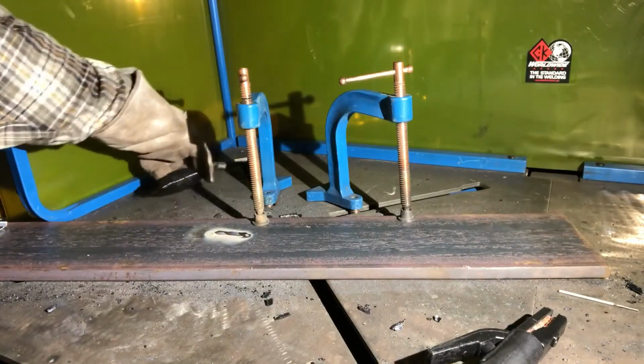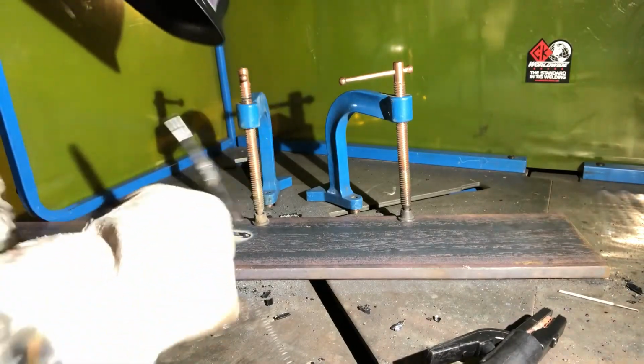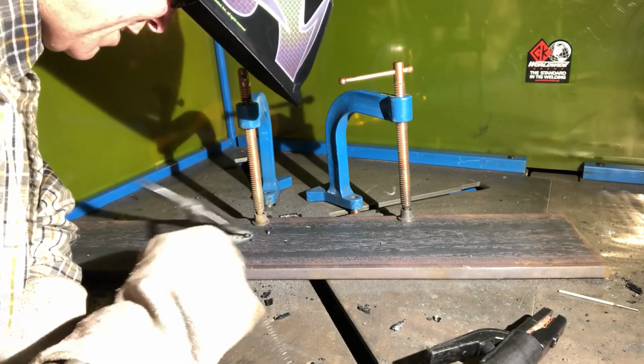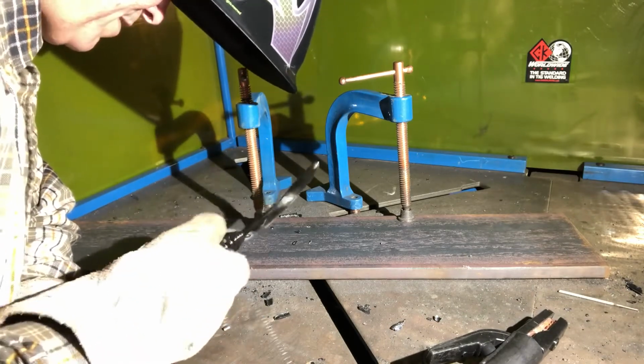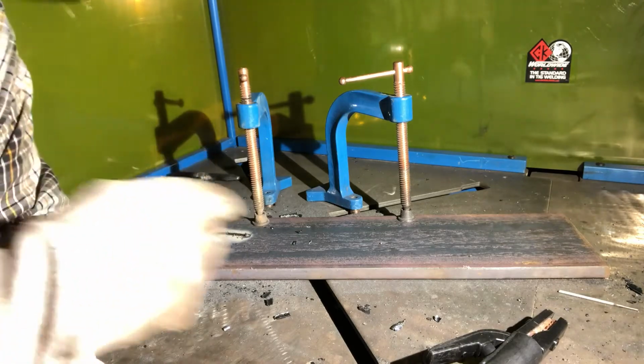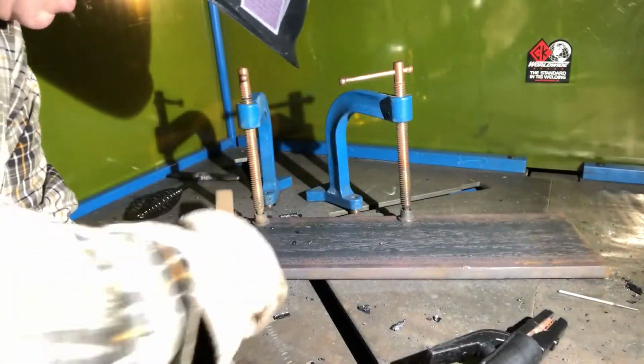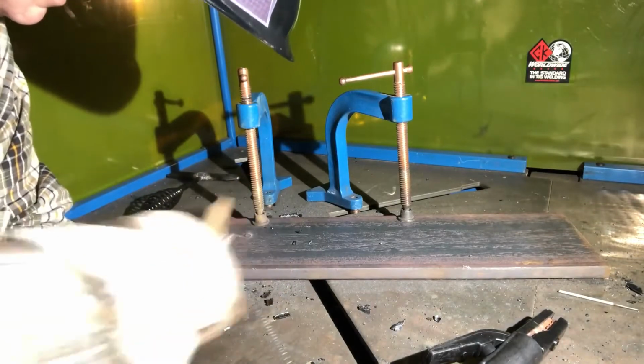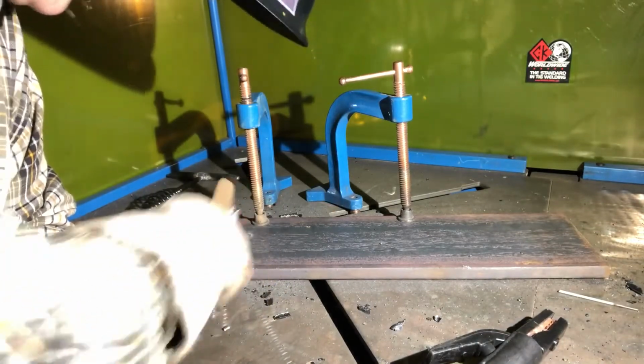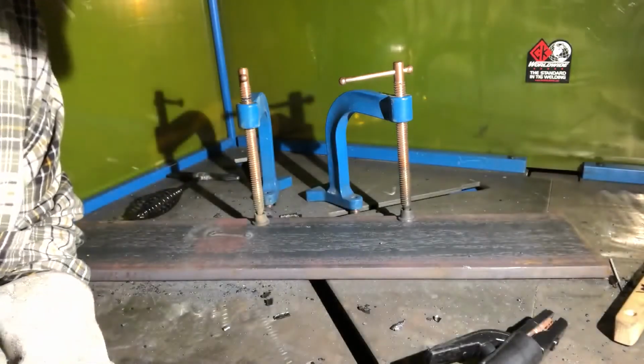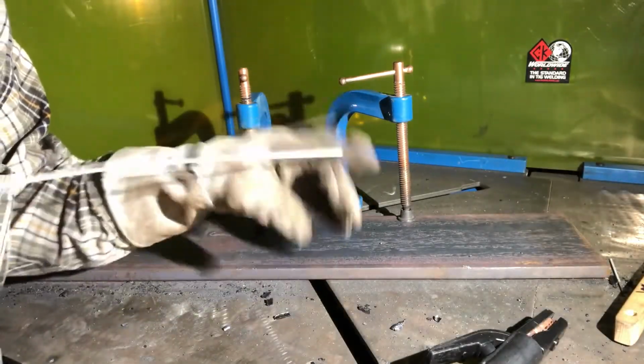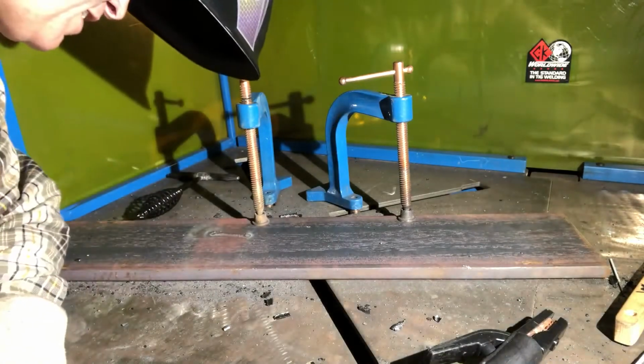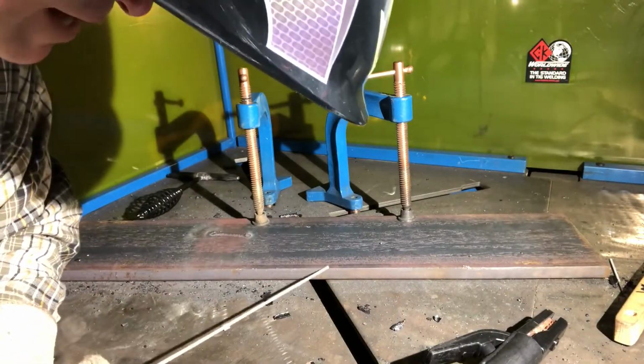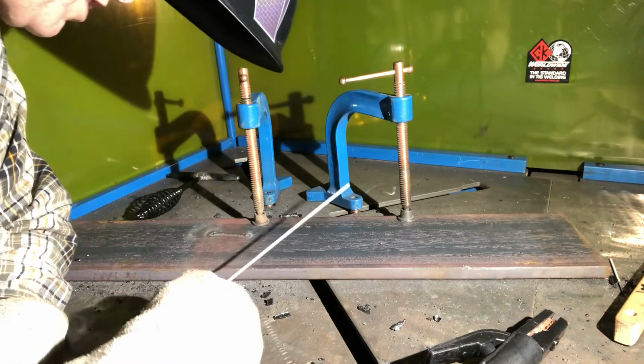Well, that was really hot. Anybody in their right mind would turn down the welder, turn down the amperage. So here's the bead. The experience of welding that was very strange. First, because the thin 1/16 inch electrode always wants to boing, boing around. And, you know, 1/16 inch electrode on 5/8 plate is really not what you're doing every day.